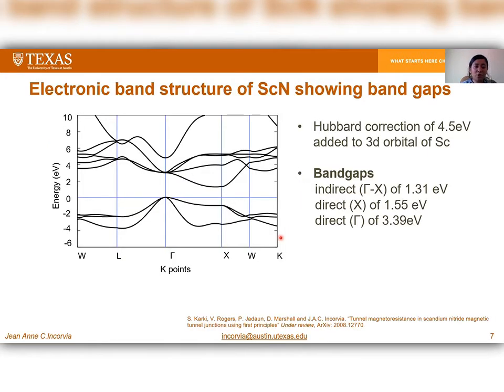Further on, we moved towards the electronic band structure of scandium nitride, as shown here on the plot. As DFT underestimates band gap, we had to use a correctional potential to match its band gap with experiments. We used a range of Hubbard correctional potentials, and we found that 4.5 eV was optimum, which needed to be added to the 3d orbital of scandium to get a band gap that matches with experiments.